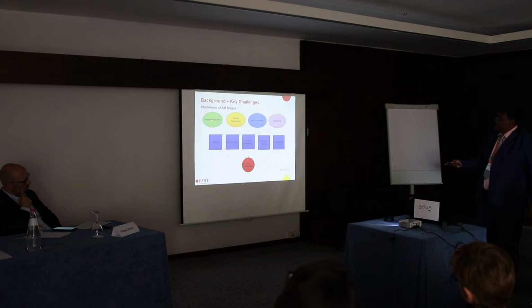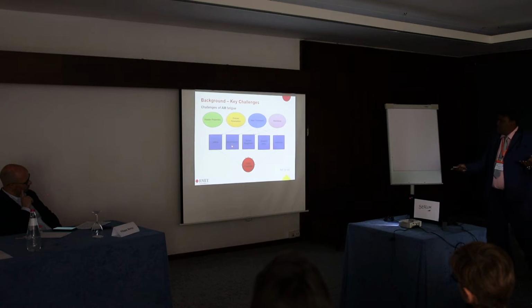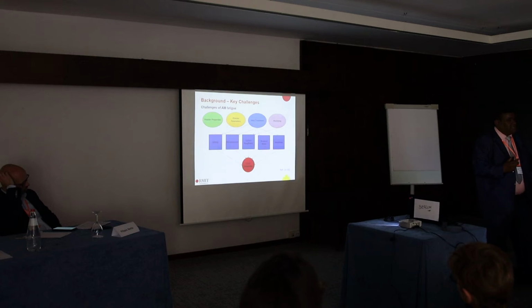So our overall challenge which we are addressing within our center is looking at the effect of these parameters: powder properties, process parameters, heat treatment, and machine. All of these are affecting the real part properties or product properties, particularly defect generation, microstructure, surface roughness, residual stress, and anisotropy. These are affected by these parameters in different ways. For example, heat treatment, which is a post-processing condition, will affect defects, anisotropy as well as microstructure. Machining will affect surface roughness. Powder properties will affect both defects and microstructure. And at the end of the day, this research is focused on cyclic properties. So you can see the interaction and interplay between complex parameters from the start, from the feedstock powder, to the end, which is the post-processing treatment on AM methods.